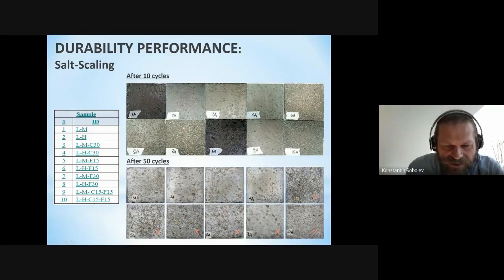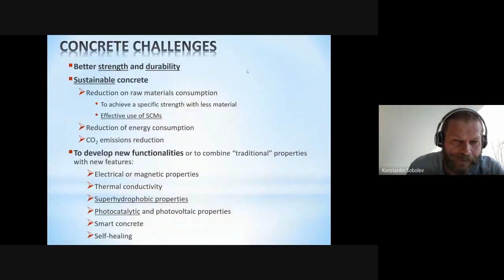Concrete based on Class C fly ash passes the test, but concrete with Class F fly ash, in any combination, really didn't pass the test after 50 cycles. So there is really concern. We have some benefits, but we still have a challenge with salt scaling.